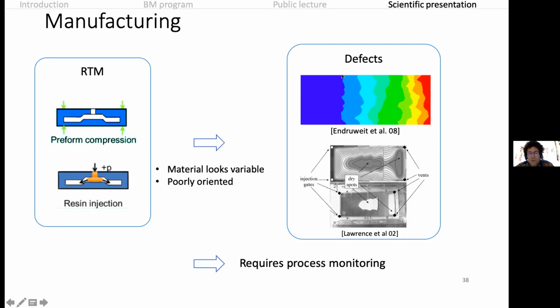The flow front is going to be variable, and you're going to have some spots that are going to stay dry before some other spots where the flow is going to go faster. So here you see that at the end, the flow reached the end on this part, but there's still some dry spots on the end. So we need to monitor this flow front. There's really a requirement to monitor the process.